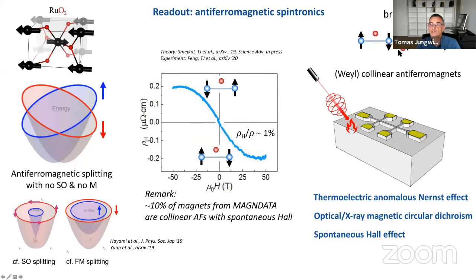Now, the trick to generate a Hall effect in these systems, in other words, how to break the PT symmetry, is to introduce additional atoms in the lattice and then place them in a position which is off this inversion center. So these atoms could be simple non-magnetic atoms, and if you place them in a non-centrosymmetric position, you will break this PT symmetry. You cannot do anymore an operation of spin flip and then space inversion to recover the original state because of these additional atoms here.